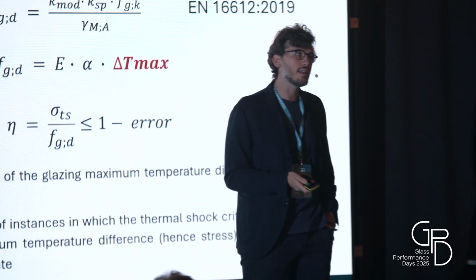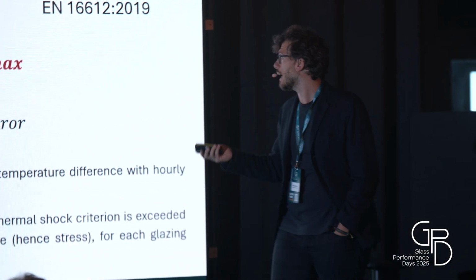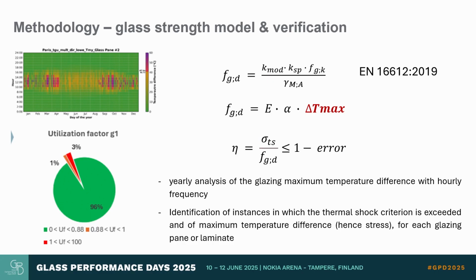This delta T is then used to calculate the thermal stress, and this is compared to the design strength of the glass, considering the EN 16612. In this case, what we use is a k_mod of 1 hour due to the hourly resolution of the climate representation, but also due to the dynamics of transferring heat in the glass, which, even in laminated glass, are about an hour. They have an hourly resolution.